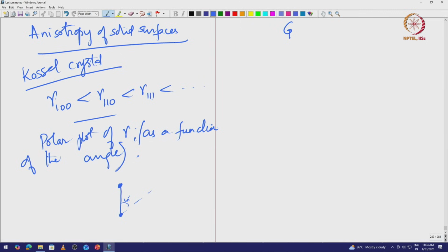and so on and so forth. So 100 has minimum energy, right, and then a slight deviation from 100 is going to increase energy. The other smaller energy comes at 110, which is at 45 degrees, then 011. In 2 dimensions, there is no 111, but if this is 100, this is 10, this is 11, this is 01, right, and that has lower energy again and again, so I have something like this here, and again this has lower energy and so on and so forth, right. So, let me just consider this as the center.